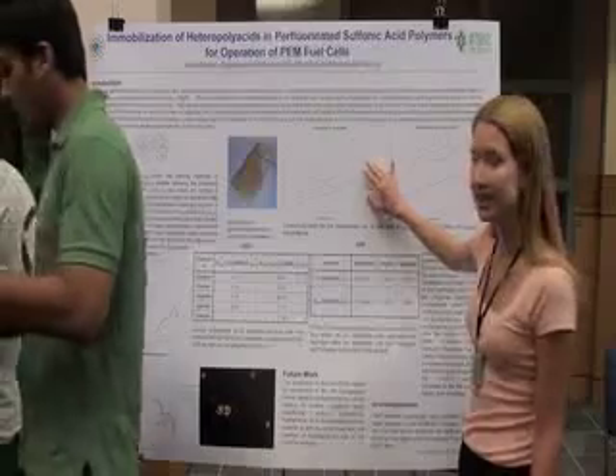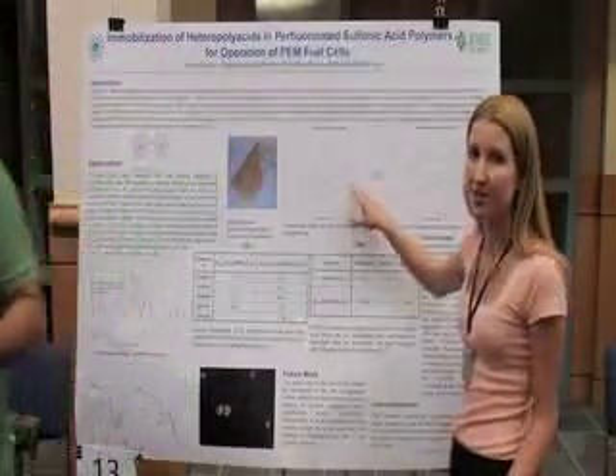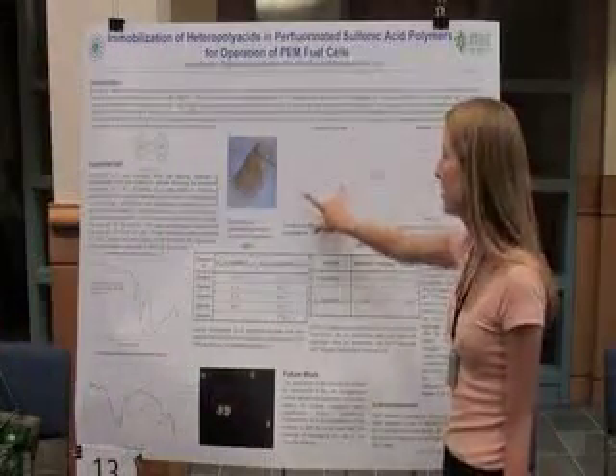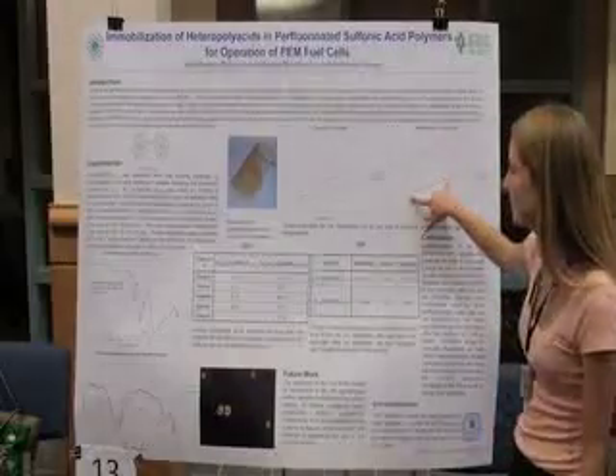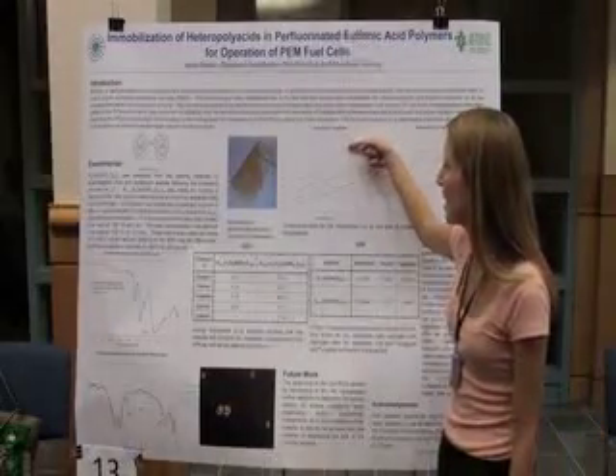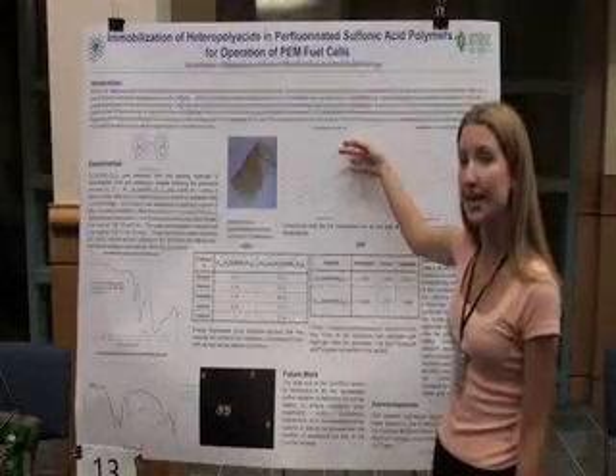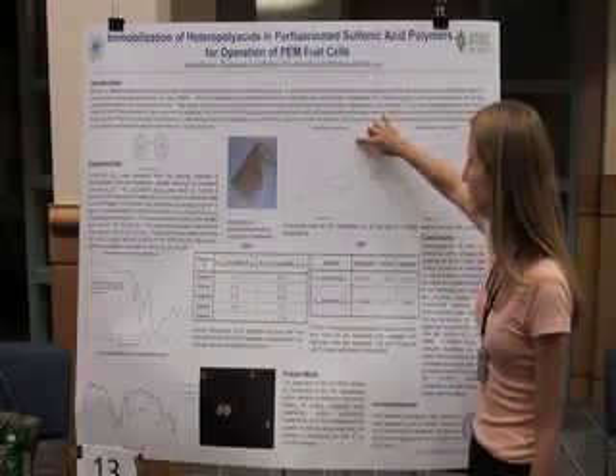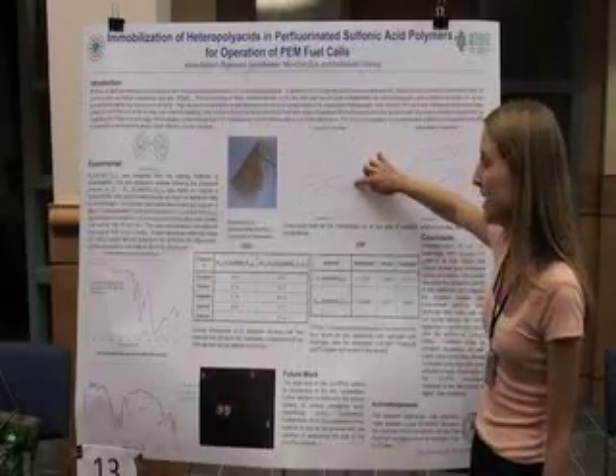So that's very good. The next thing that I did, after the membranes were cast, was to see how well they were actually conducting compared to the state-of-the-art 3M ionomer, which is this bottom blue ionomer here. These are the ionomers that have been loaded with the HPA. This is 0.5%, 1%, and 2%.